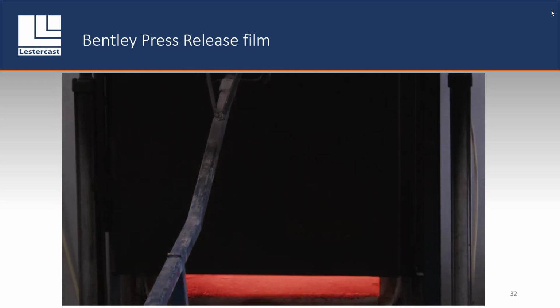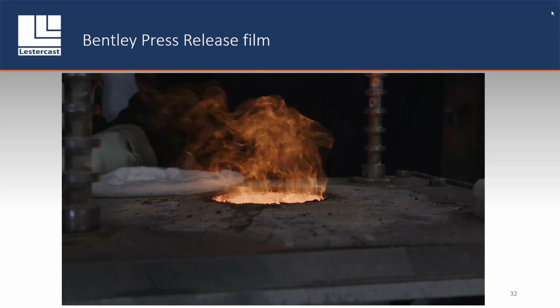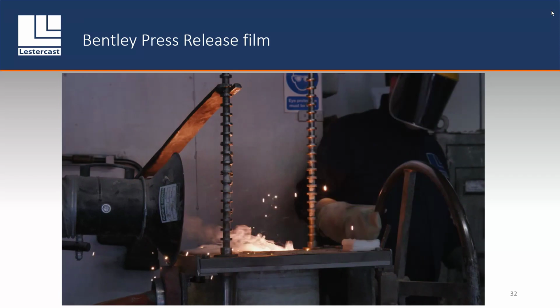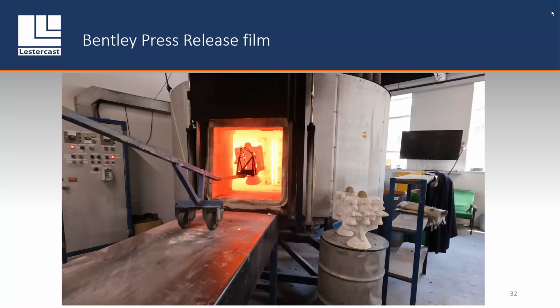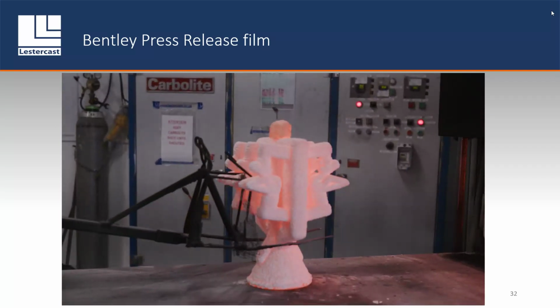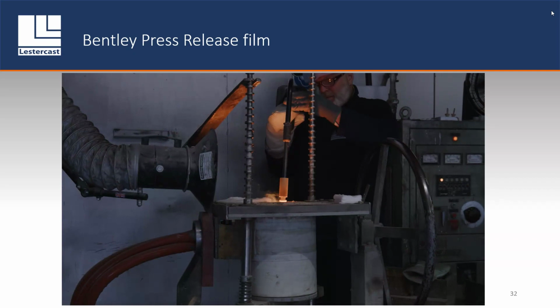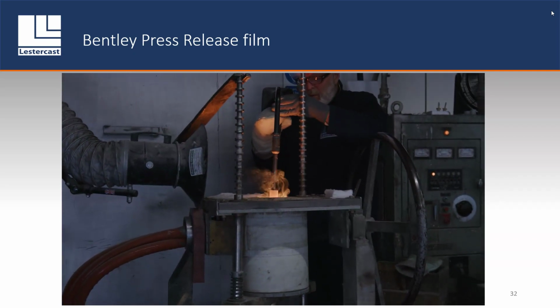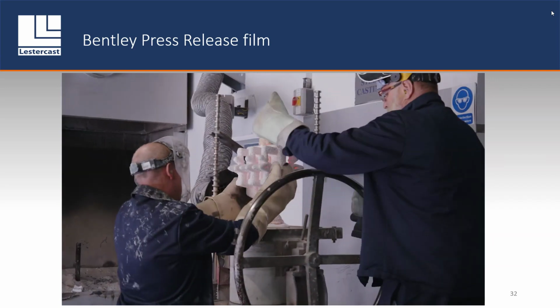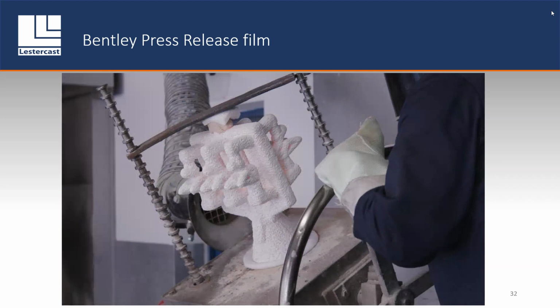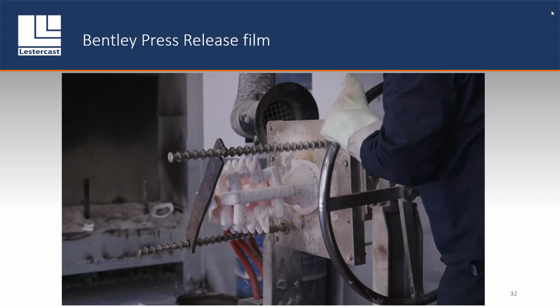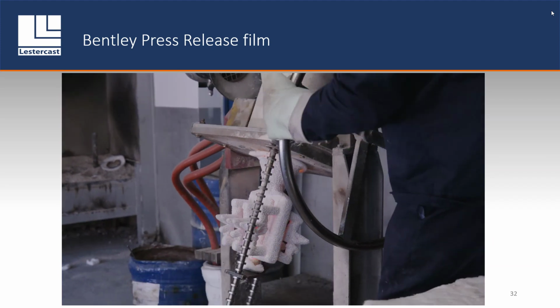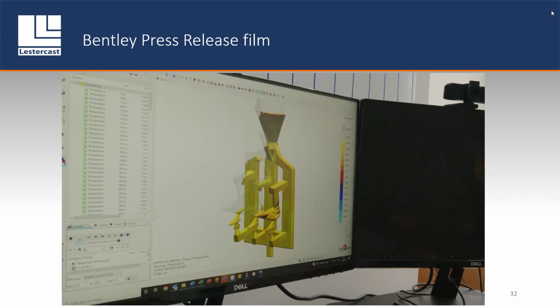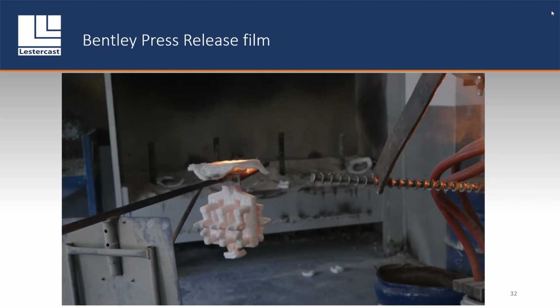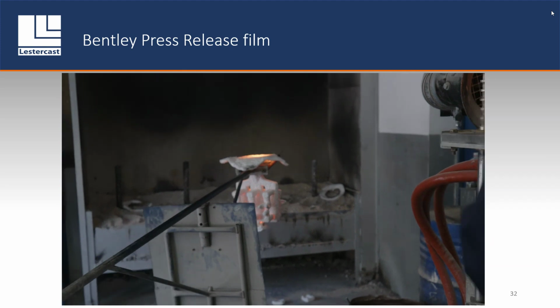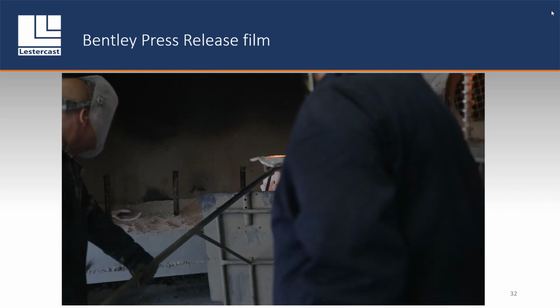After de-wax, we then preheat in a preheat furnace, heating up to 1,000 degrees for the shell. And once the mold is ready, it removes any residual wax that's in there. It's also firing the shell, and it's preheating, ready for casting. So we're casting at around about 1580 degrees C. The mold is offered onto the furnace, as Russell described earlier. The furnace rolled over, contents of the furnace deposit into the shell, and then the shell is put aside for cooling. So you can see there what we've replicated in simulation is what we've got in real time. The mold is put aside till it's cool enough, then we can remove the shell.